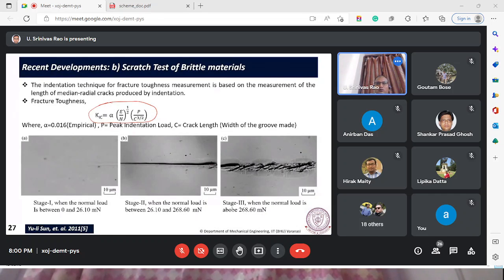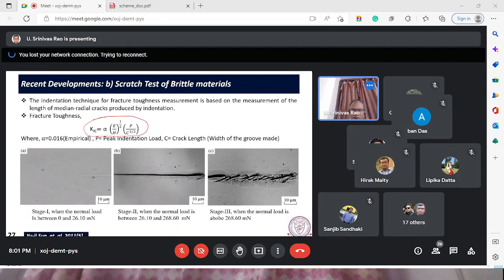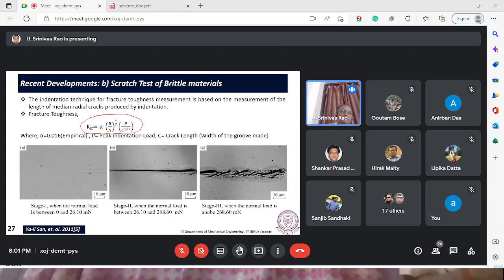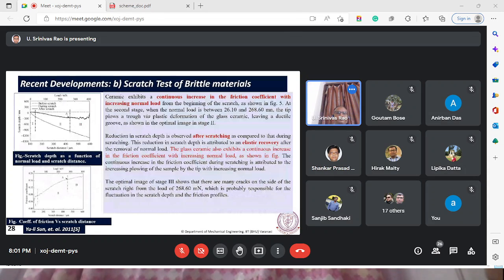Then a scratch is getting formed, but there are no lateral cracks. Then in stage 3, you have a lot of lateral cracks. From this, we can find out the transition phase, where the formation of lateral cracks marks the ductile-brittle transition. Initially, it is ductile mode. Then, when the load is further increased, it goes to brittle. From there, we find out the critical depth information and the fracture toughness at that load.